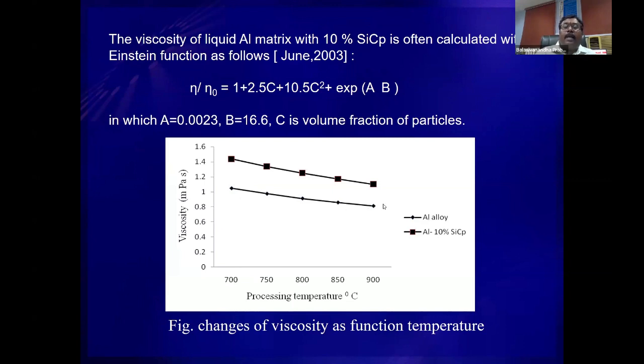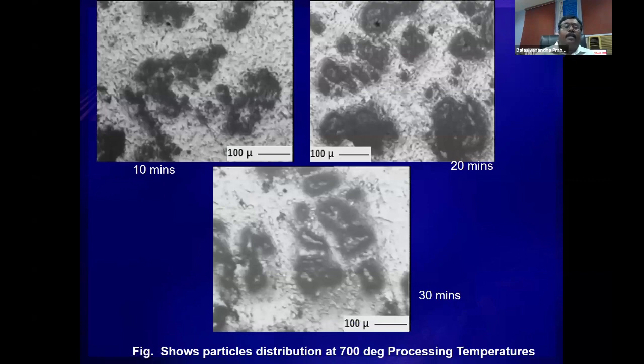So probably at 900 degrees centigrade, I would get a viscosity similar to the pure metal. That would be possible, and now you can disperse the particles. So here I present the three cases. One, the melting temperature 650, preheated to 700 degrees centigrade, where particles are stirred and cast.